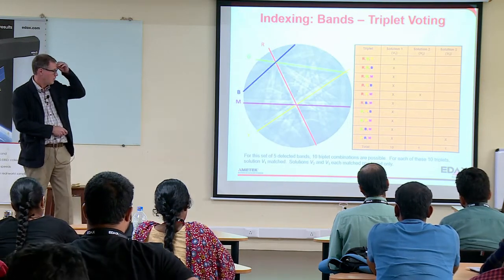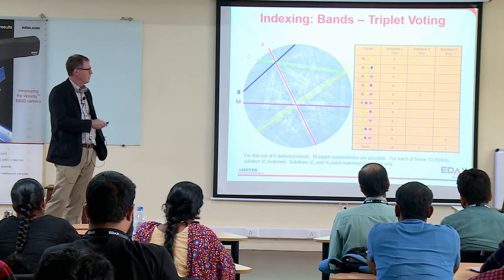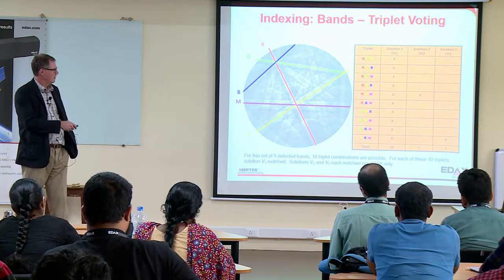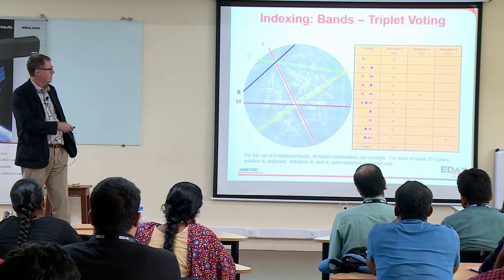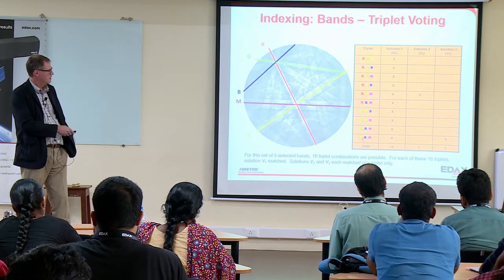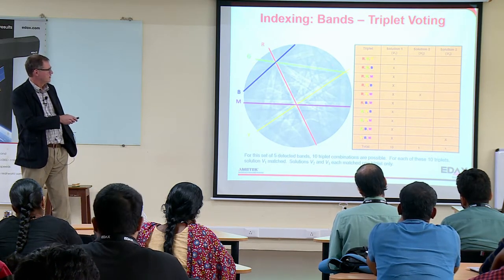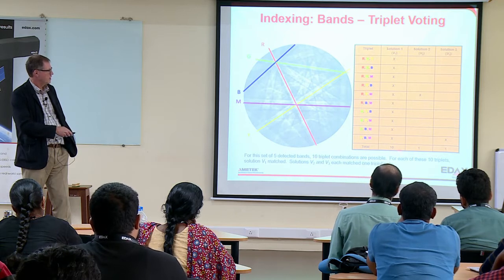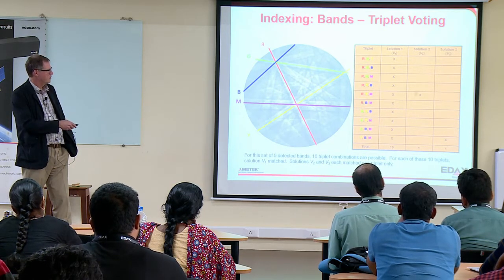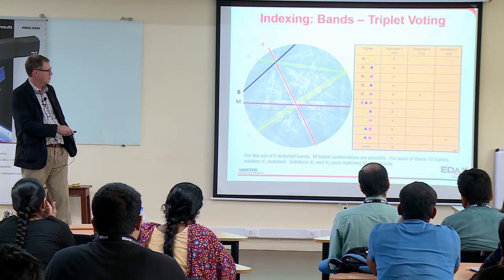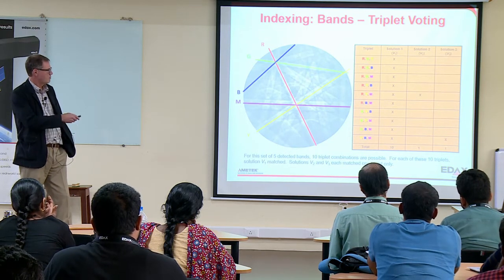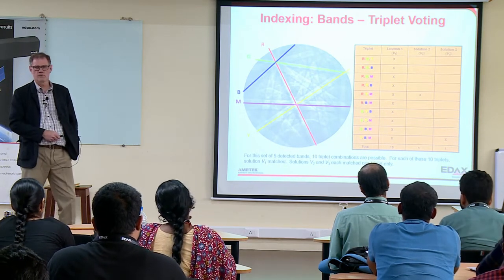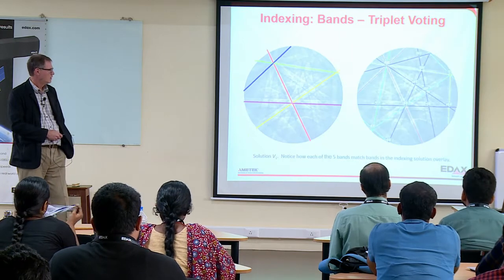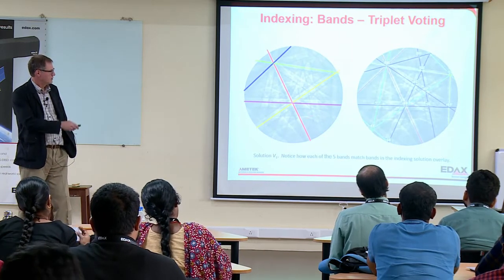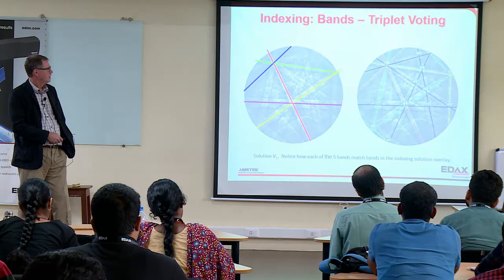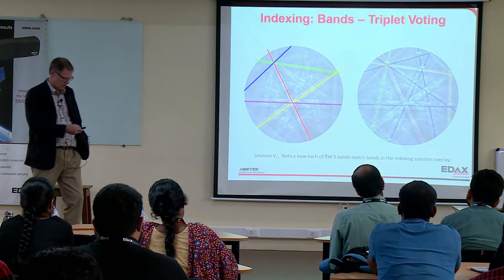And this is then how we do it. We use a voting scheme. So right here I have 5 bands. I have, I think, 10 possible triplets. The first solution appears 10 times. We get a second solution that appeared once and a third solution that appeared once. And so this is our most probable solution according to our voting. And so you can see here it fits nicely, and it does a great job.